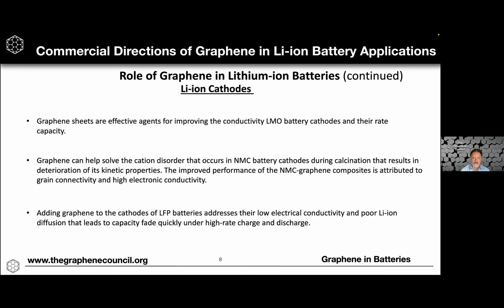Finally, as far as the cathodes are concerned, adding graphene to the cathodes of the LFP batteries addresses their low electrical conductivity and poor lithium-ion diffusion. And these factors can lead to the capacity fade during charge and discharge.